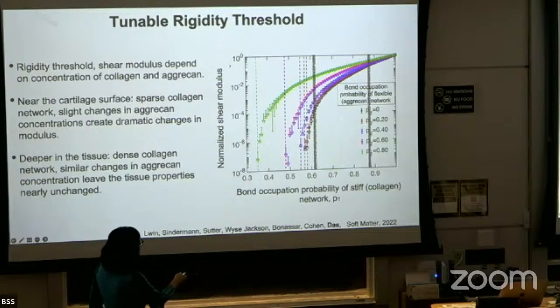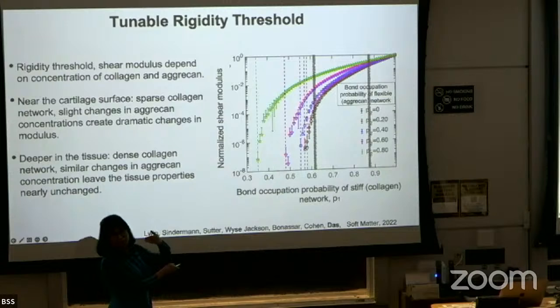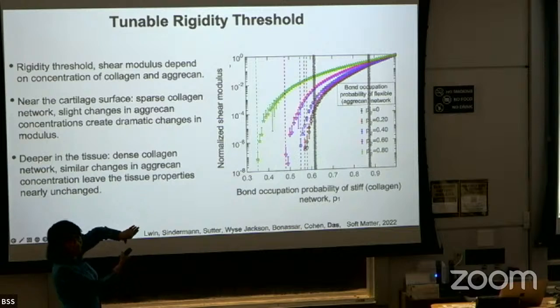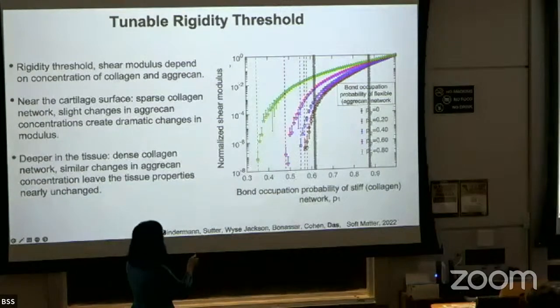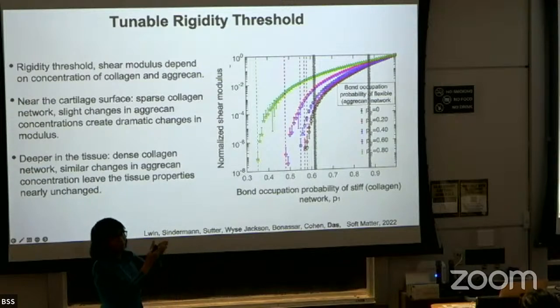In the case where we had only one network, and I'm using a Kagome lattice-based network, by the way, not a triangular lattice, for reasons that I described previously, if there was no secondary network, the percolation threshold would have been here. But as you have a secondary network and more material in the secondary network, you can see that the percolation threshold shifts further and further. So you need less material in the stiff network if you have constraints from the other network. The normalized shear modulus of the composite network is also larger if you have more and more material in the secondary network, also from the constraints.